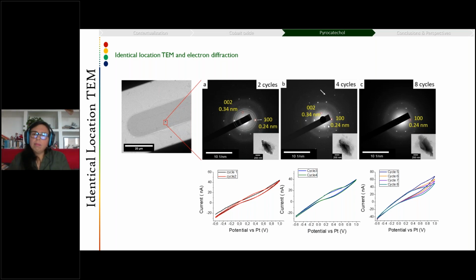If we continue cycling, we are able to find again the same patch, and we see that these crystalline spots start to become more and more clear and go towards a monocrystalline structure. And that's what happens towards 8 cycles. And we effectively see the decrease of the current during the cycling, which means that the structure that is forming is less electroactive than our starting material, which would go with the idea that we are forming a carbon, graphite oxide material.